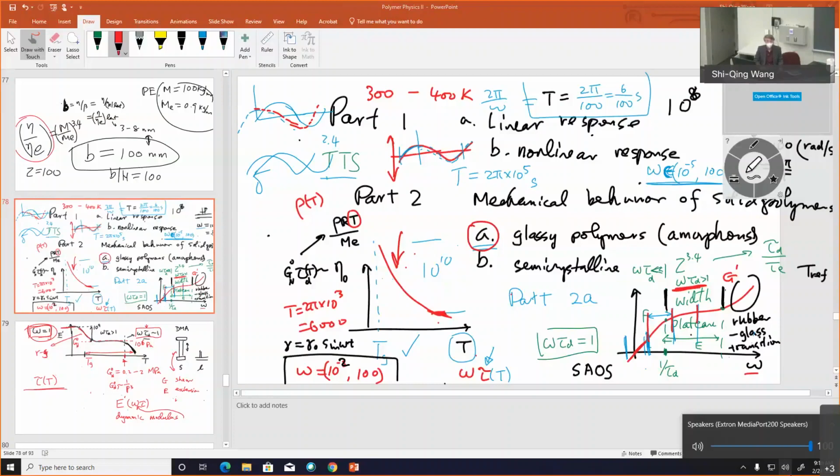Not really. So your Tc, crystallization temperature, truncates your ability to do time-temperature superposition. All you can do is go prior to when it crystallizes. Because your intent was to interrogate your molten state, your melt state, in absence of any other structures.